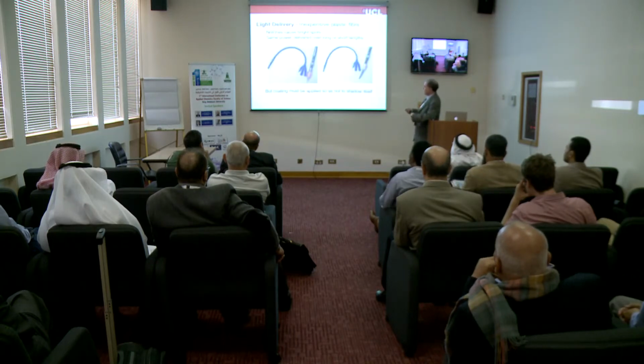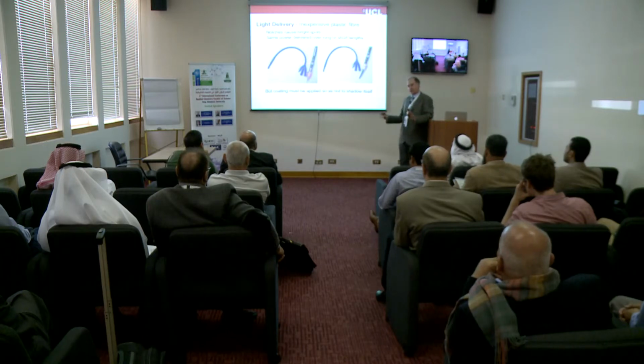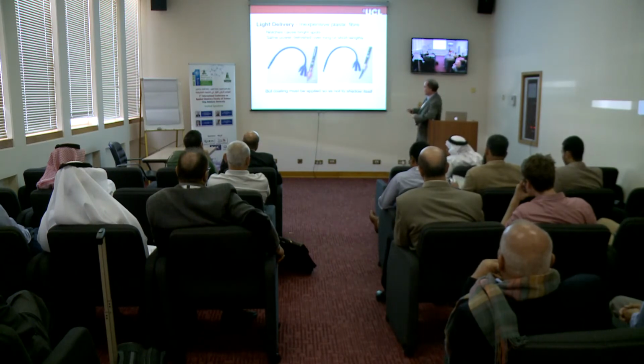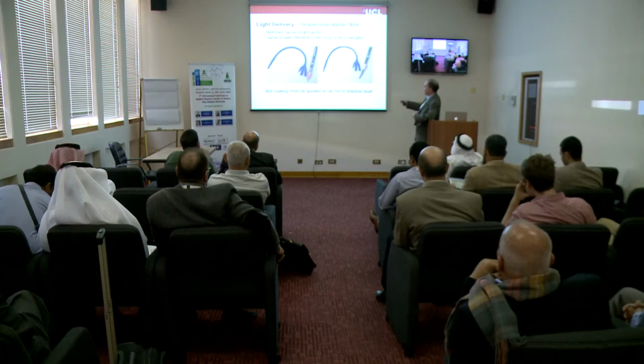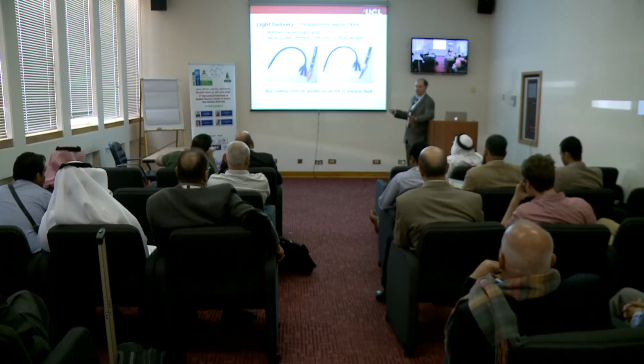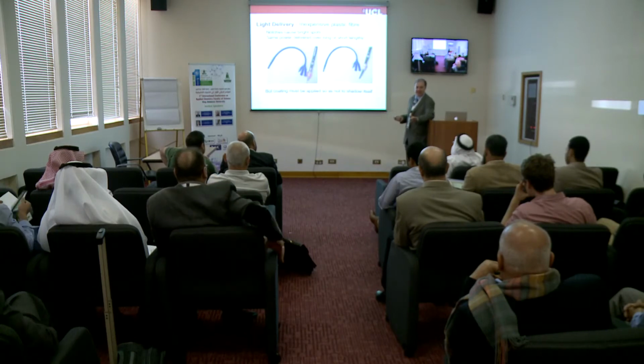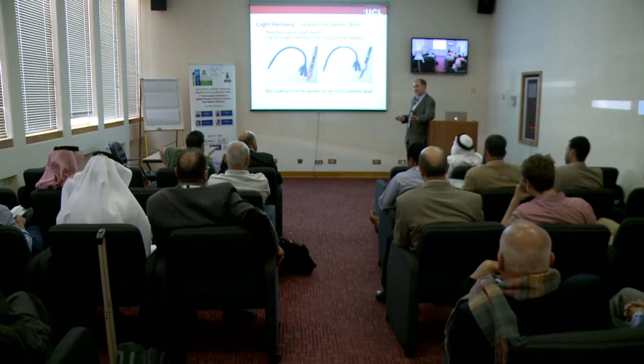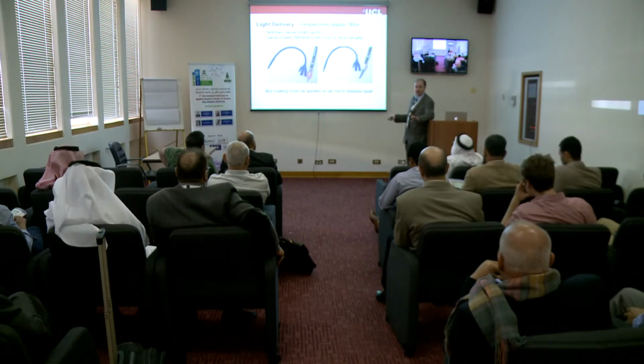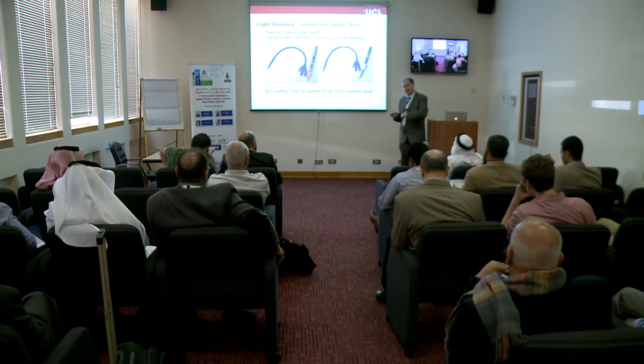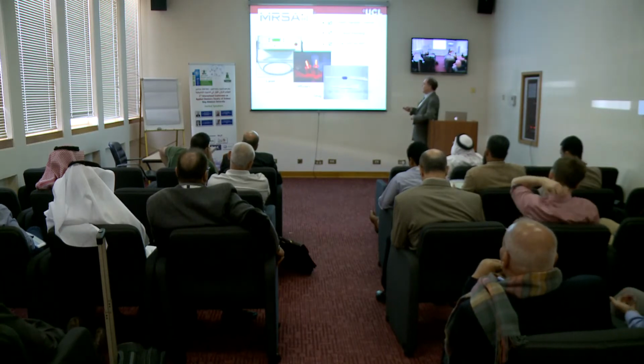We've also looked at commercializing this, and this is an example of a catheter. Catheterization is the number one procedure in all hospitals throughout the whole world, whether it's in blood, for urine, whatever, but this is the number one process. And what we've developed is a laser fiber which goes inside the catheter. This has our light activated agent, and when we turn the light on, this actually disinfects the catheter and stops people getting catheter-related infections. If you are a catheterized patient, you have a 10% chance additive every day of getting an infection. So if you've been catheterized for 10 days, you will have a hospital-acquired infection. That can be treated with antibiotics, but there are less antibiotics available at the moment because there's so much resistance developed by bacteria. So this strategy tries to prevent people getting infection in the first place.